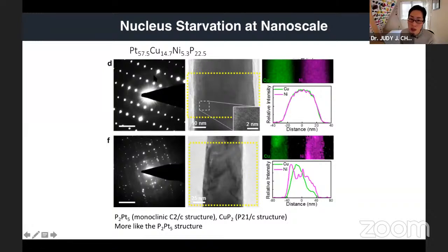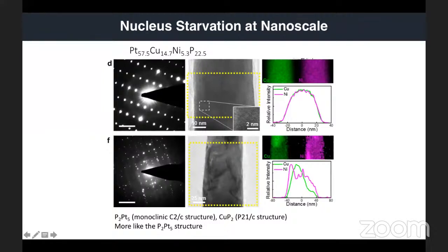If you want to do it, what you need to do is to tilt your nanorods in at least 3 different crystallographic orientations and get the diffraction pattern. But these are about 30 to 40 nanometer wide rods, so it is kind of difficult to tilt them in the right orientation. So we just have this single diffraction pattern, and we think that it's similar to this structure, but we don't actually know the crystalline phase. Okay. In fact, I got this type of metal cluster compound with a similar type of pattern, so I was curious about indexing.